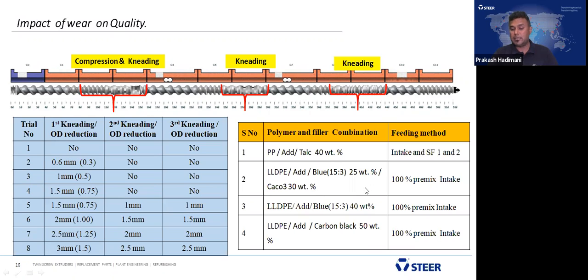It's a combination, all three put together in a high-speed mixer, made into a 100% premix fed from the intake. And the third application, LLDPE and blue pigment, is a monopigment, 40% pigment, 100% premix in a high-speed mixer. We fed it from the intake through the screw extruder. And the fourth application, LLDPE with carbon black, 50%, 100% premix in the high-speed mixer and fed from the intake.